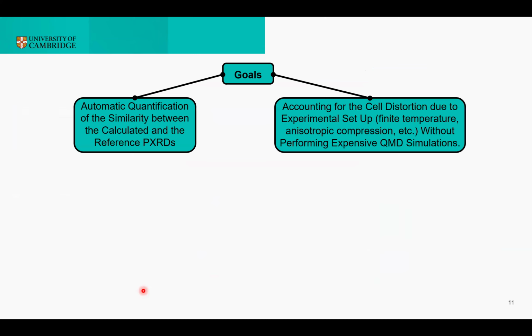Therefore, I tried to improve this procedure, and in particular, I wanted to achieve a couple of goals. The first one was to implement an automated quantification of the similarity between the calculated and the reference powder diffraction, that was supposed to be the experimental one. Then I wanted to have a method that could account for all the deviations from an ideal crystal structure. So incorporating deformations that could emulate or simulate the finite temperature or anisotropic compression that would happen in a real structure. But I wanted also to do that on the fly, so without the need to perform expensive quantum mechanical or quantum molecular dynamics simulations.